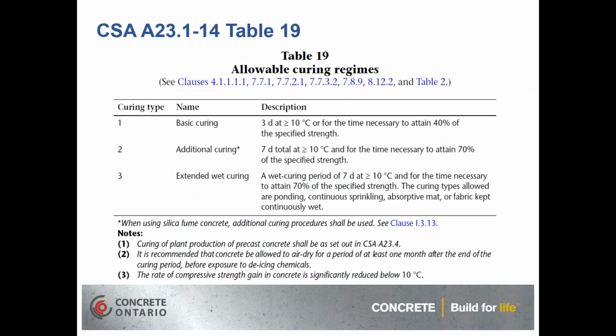If you're looking at curing type 1 for basic curing, which is for 3 days at temperatures of 10 degrees C or higher, that is for the time necessary for the structure to attain 40% of the specified strength. The most common type of curing is number 2, additional curing, in particular for exterior flatwork applications, and that's for 7 days at ambient temperatures of 10 degrees C or higher, or for the time necessary to attain 70 to 75% of the specified strength. Not always easy to do in winter construction, but we need to be mindful of this and make sure that concrete has appropriate temperatures to reach its strength and durability.